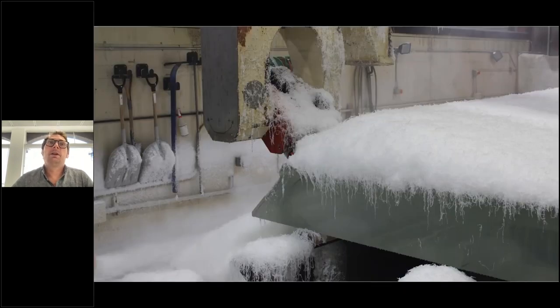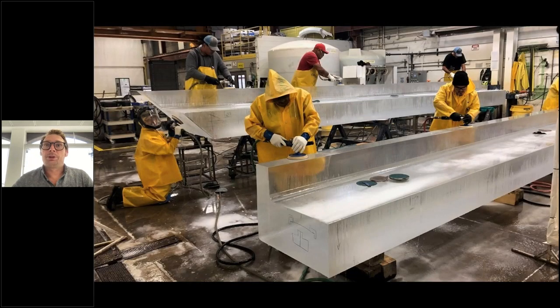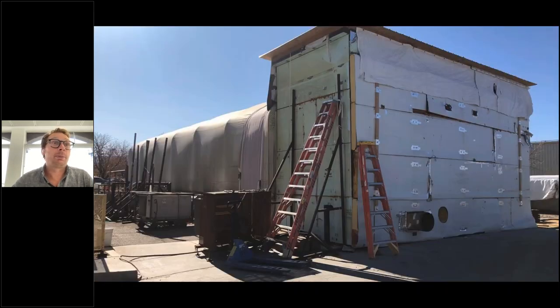These are machined by a four-axis milling machine that was developed solely for this purpose. And there was a lot of hand polishing, making sure the edges are in line and have as close to zero defects as possible was very important, because of the clarity of the material, you tend to see every defect. They had to build an external oven, an autoclave, just an oven, to control the temperature during the bonding and to anneal the material as well.